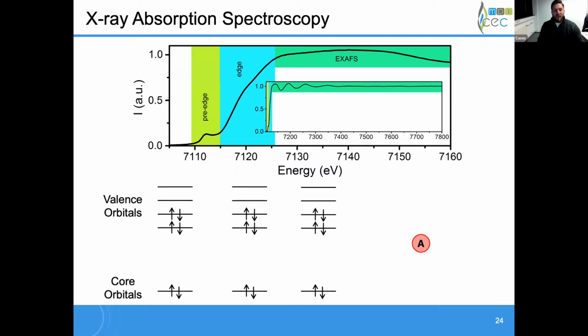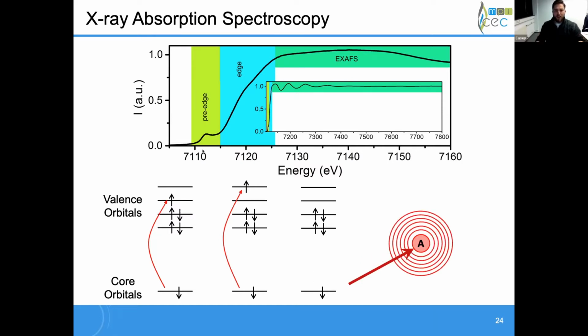All right. So of course, I'm giving a talk to a series of X-ray experts, but I like to keep a little bit of a simple pedagogical component to my talks. So I thought it would still be worthwhile to have this. In X-ray absorption spectroscopy, as most of you know, we basically irradiate an absorber of interest with X-ray radiation. At a certain point, as we move up in energy, we can start exciting from core orbitals to our valence orbitals. Depending on the nature of our sample, we could have pre-edge features or other edge features. As we continue to increase that energy, we have absorption and excitation to higher and higher energy bound states, until we hit a certain point at which the kinetic energy of the electron can break free from the potential of the nucleus, and it goes out into space and propagates out as a photoelectron.